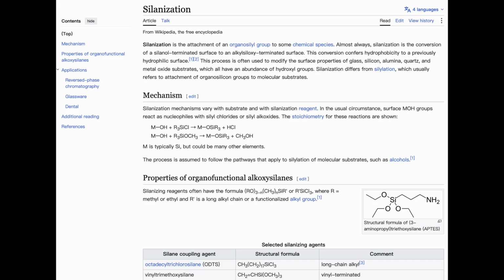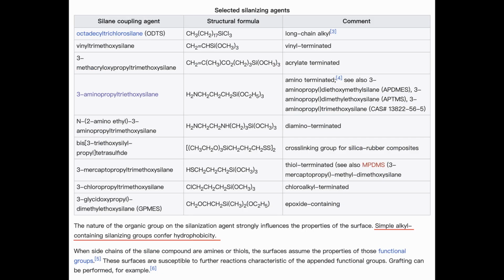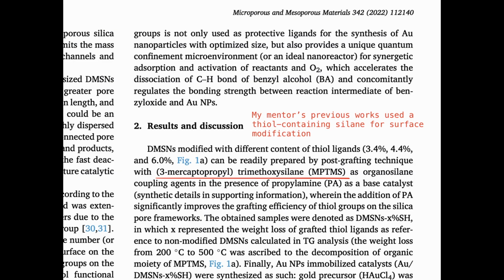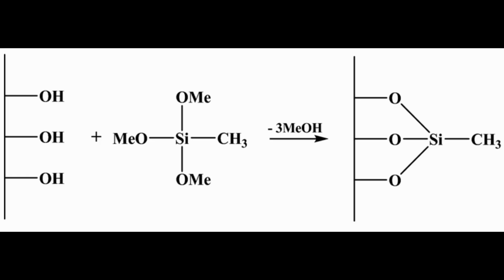Anyways, we proceed to the next and more critical step, a hydrophobic surface modification, which involves using an organic silane reagent to add alkyl tails to the currently hydrophilic silica surface. The most common reagent of choice is methyl trimethoxysilane, which is added to a suspension of DMSN-acid in toluene, followed by addition of triethylamine base.